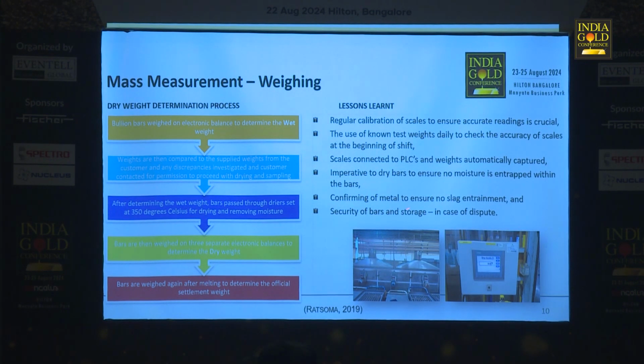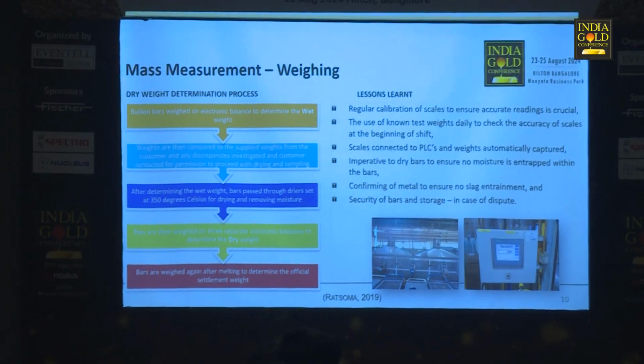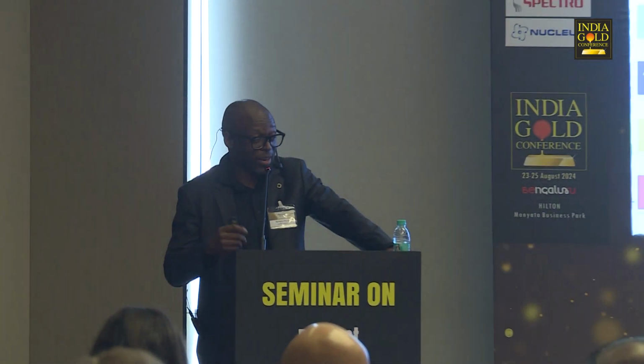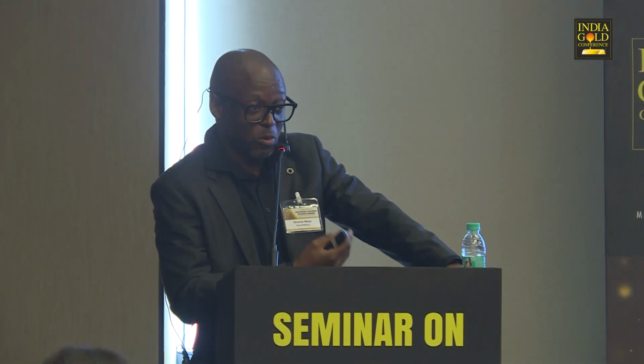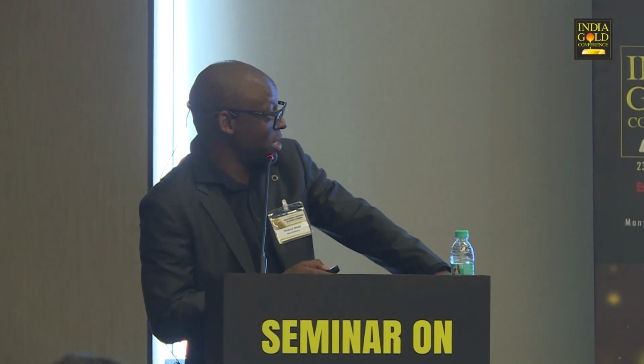And then because we're predominantly a gold mine refiner, some of the bars that we do receive have got slag entrainment. So it is important that after we've confirmed, after taking samples, we need to make sure that we don't account the slags as part of the gold metal. And then maybe on this last side, we've invested as well in security measures to make sure that before the gold is released, if a customer can have a dispute, everything is under observation. We've got a security surveillance system to make sure that there are no issues. Anyone can come and dispute, to see if, let's say, we were to pronounce the results, their question, they can see it on video surveillance.